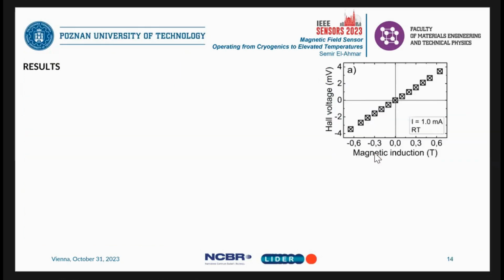But what I can show you today are a few things. Here you can see the standard dependence of the signal of our sensor, the Hall voltage, versus the induction of the magnetic field from -0.6 to 0.6 Tesla in both polarities of magnetic fields. It was a measurement made at room temperature at a driving current of a single 1 milliampere, and you can see that it's a quite nice linearity of the signal versus magnetic field.